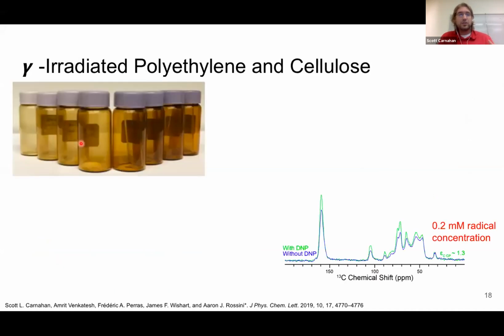So before I show this picture of the vials and the vial caps, where you can see the irradiation damage, one thing I did was I just took a vial cap, ground it up, and did DNP on it. With essentially zero optimization, no field sweep, nothing, I just took one vial cap and I didn't try to optimize the gamma radiation amount. We were able to get a small enhancement.